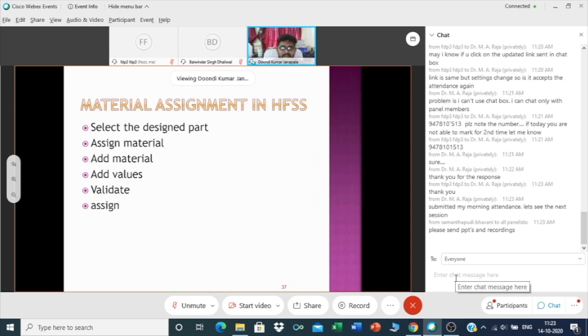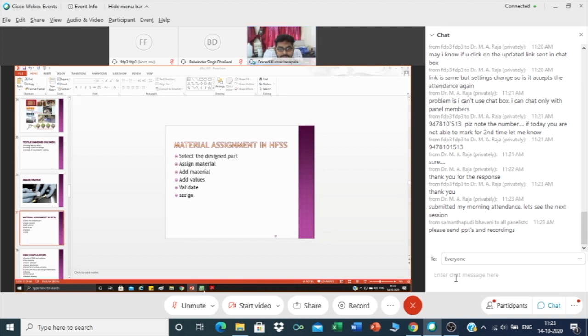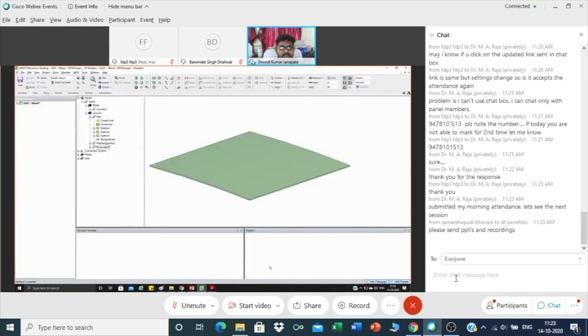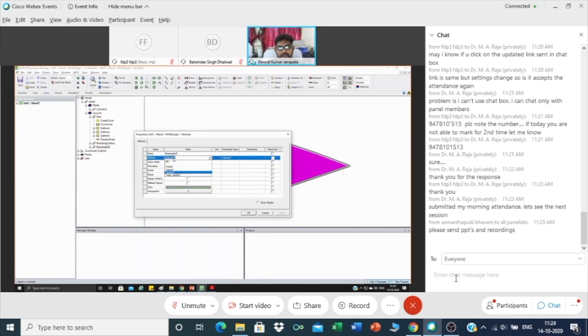So, material assignment in HFSS. Probably I will show you simply. Here, simply select your particular substrate, and you go here. Normally, it's filled with vacuum. You go to edit, go for add material. Suppose you made a PDMS, you type PDMS, and go for relative permittivity 2.7 and dielectric loss tangent around 0.0314, and validate your material and press OK.